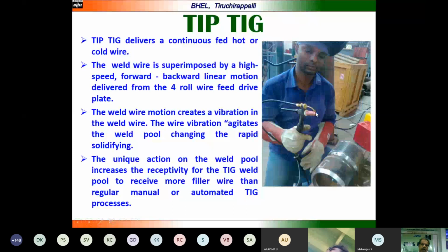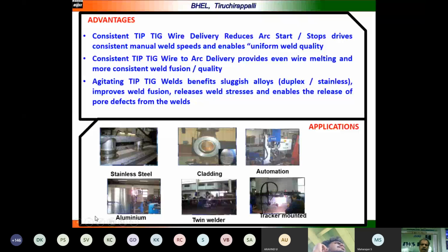The weld wire motion creates a vibration in the weld wire. The wire vibration agitates the weld pool, changing the rapid solidifying, and as the weld pool agitation increases, the TIG weld pool receives more filler wire than the regular manual or automated TIG welding process. That is the advantage of this process actually. And consistent TIP TIG wire delivery reduces the start-stops, there are no start-stops actually, and it provides even wire melting and more consistent weld quality, and these are the advantages.